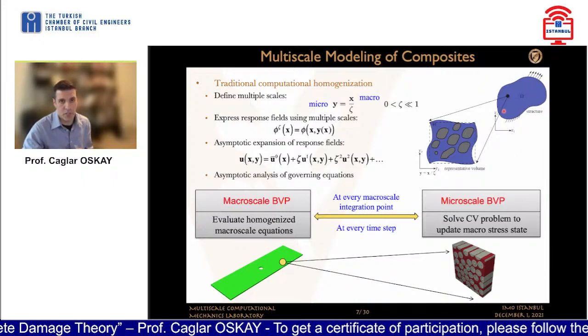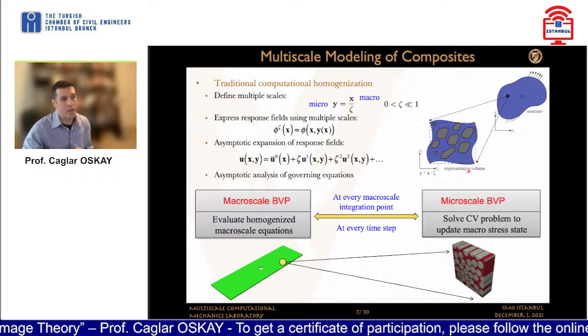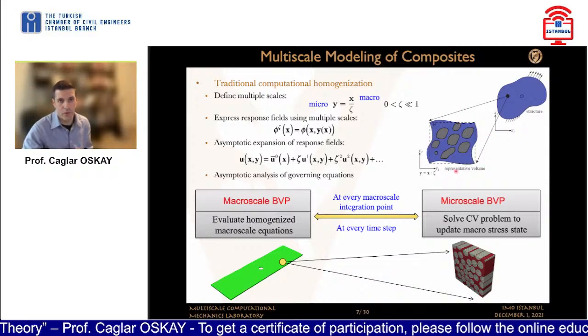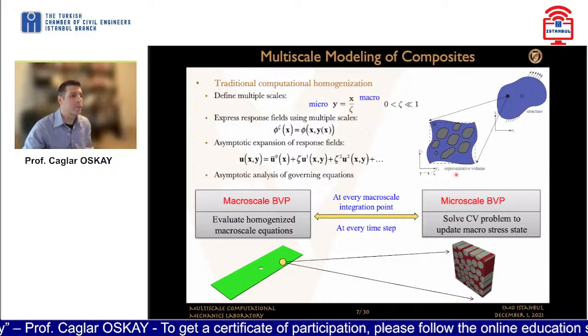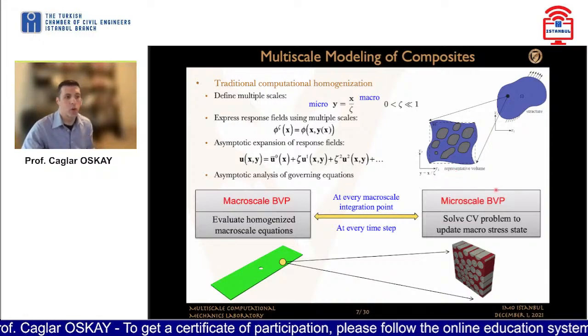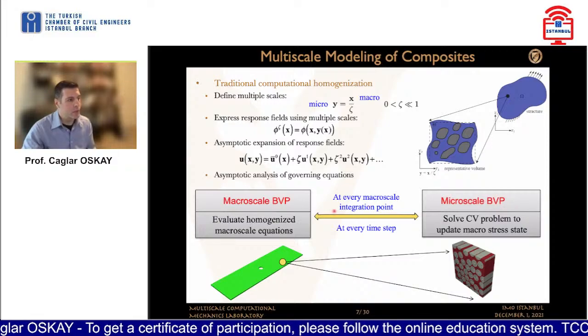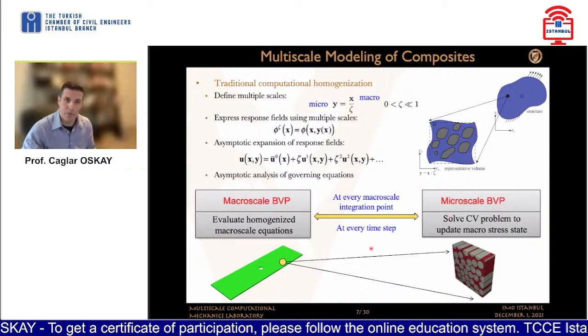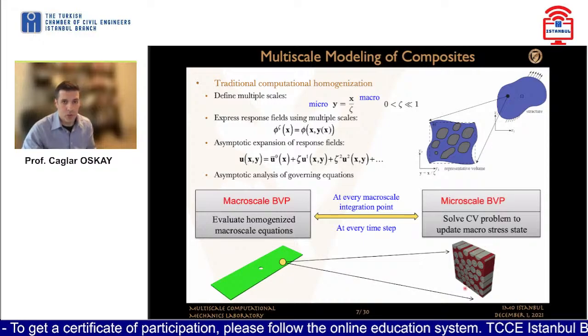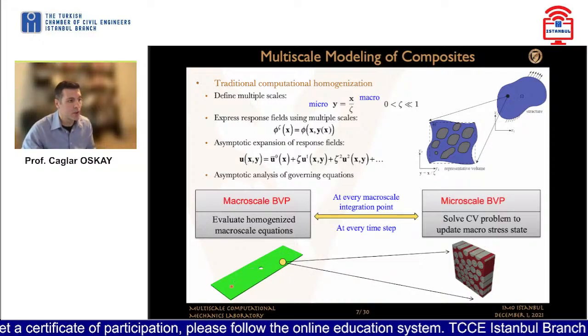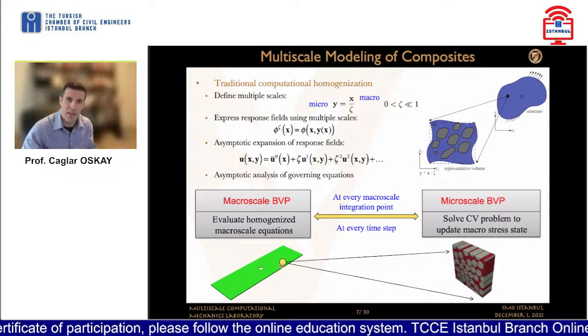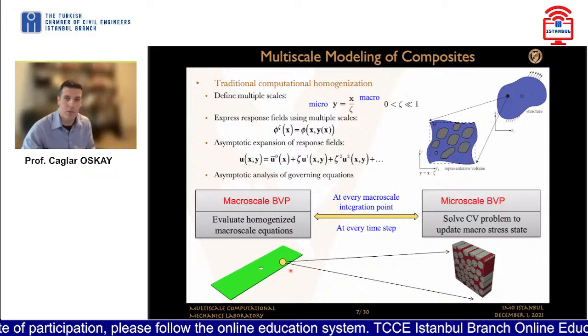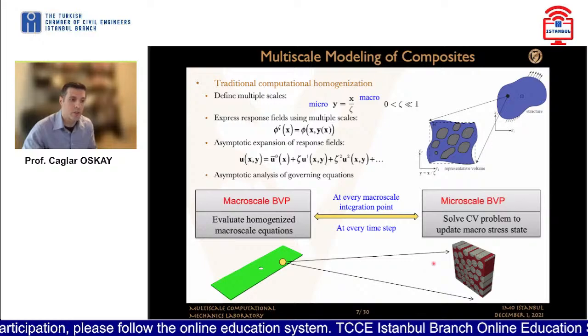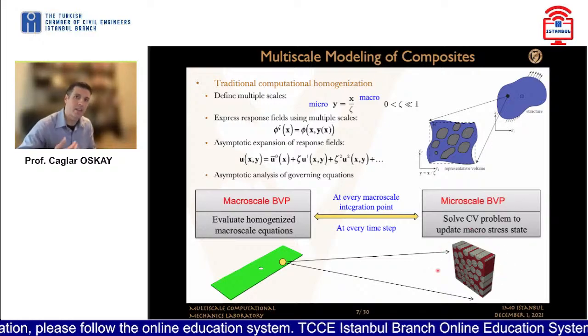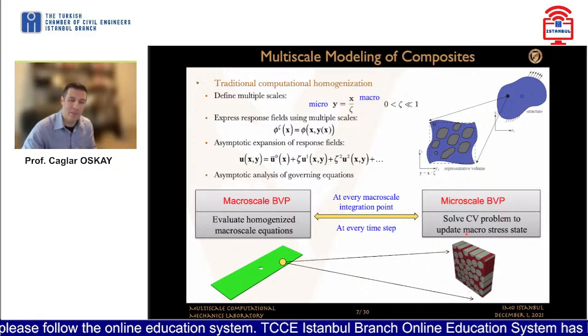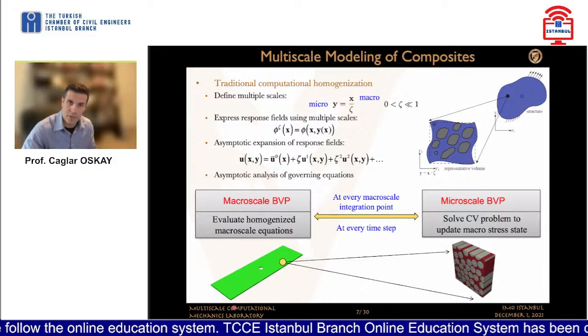That's called the macroscale problem. And then microscopic structure defined over the representative volume or a unit cell, and that is called a microscale problem. We solve these two problems in a coupled fashion, in that there is a microstructure associated with each material point. In this case, if you're using finite element analysis to solve the macroscopic problem, at each quadrature point, you associate and track the evolution of damage within a different material microstructure throughout the system.